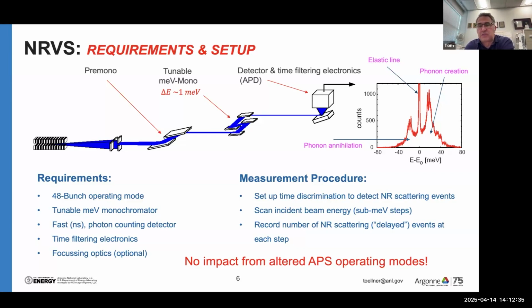So you see you have an elastic line when the incident beam is aligned to that, and then you see the 2 sidebands. And so the mono needs to scan. All you do here is you scan the monochromator, you scan the incident energy, and basically time filter out any resonant events that occur between the X-ray flashes. Here, the width of the time window is not critical, as long as it's not too small, so that we have some reasonable time window.